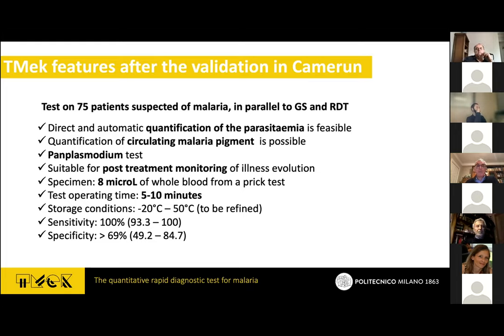So it was for us quite a big success at that time. And these were the figure of merit at that time. Essentially, at that time, we obtained the first demonstration of a system which was suitable for a direct and automatic quantification of parasitemia. And the interesting story is that this test is in principle a pan-plasmodium test, which means that all species can be detected because we are detecting the production of the hemozoin, which is common to all species, which means Plasmodium vivax, malariae, and ovale, all the other species can be identified.